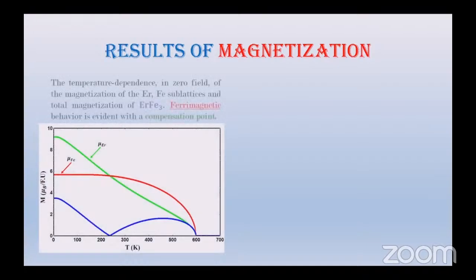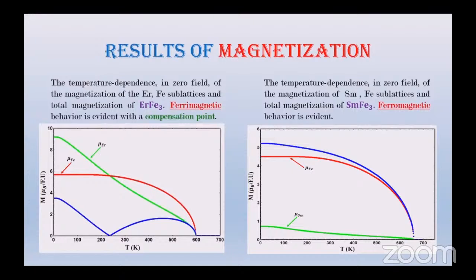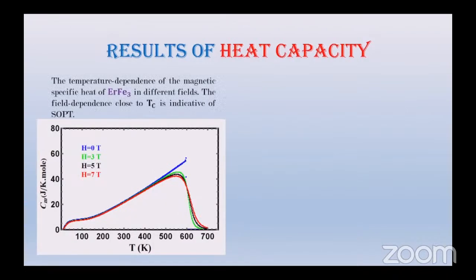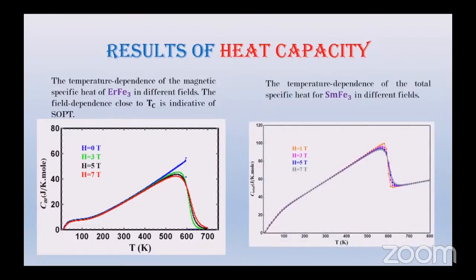Results of magnetization. Our simulation for the erbium iron 3 magnetization shows a ferrimagnetic coupling with a compensation point at 220 K, while the samarium iron 3 shows a ferromagnetic coupling, in agreement with available experimental data. Results of heat capacity. The temperature dependence of the magnetic specific heat of erbium iron 3 in different fields shows a field dependence close to Tc, which is indicative of a second order phase transition, and the total specific heat at different fields is shown.